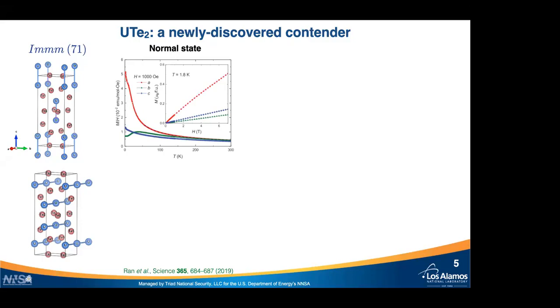It's orthorhombic, so it's anisotropic. A, B, and C are not equivalent. But one thing to point out is that along the A-axis, we have a larger magnetic susceptibility, indicating that that may be the easy axis of this material, at least at ambient pressure.